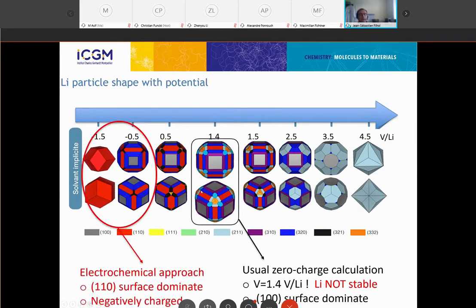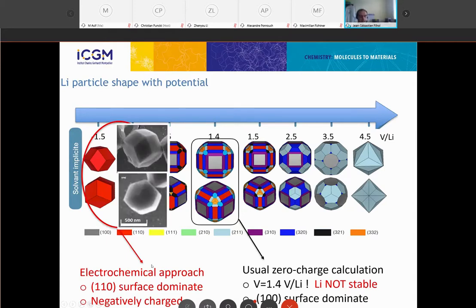So to get to a negatively charged system, going to zero relative to lithium, we can get a charged system, and we find that we get a completely different surface. When it's uncharged, it's a 1,0,0 surface that dominates energetics, and when it's under reduction, under negative potential, it's a 1,1,0 surface. And in this case, you see that we are able to reproduce the shape of the lithium particle. So it's one thing to say that charged surfaces are really important to get proper surface and interface energetics.